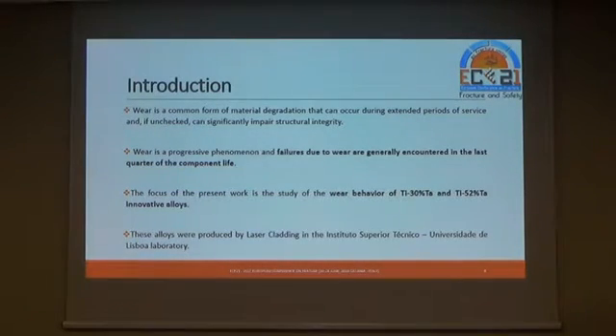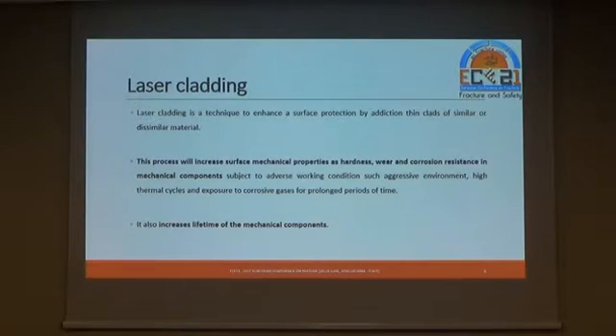These alloys were produced by laser cladding at the Instituto Superior Técnico of Lisbon University in Portugal, of course. Laser cladding is a technique to enhance surface protection by addition of thin clads of similar or dissimilar material. This process will increase surface mechanical properties such as hardness, wear, and corrosion resistance in mechanical components subject to adverse working conditions such as aggressive environments, thermal cycles, and so on. It also increases the lifetime of the mechanical components.